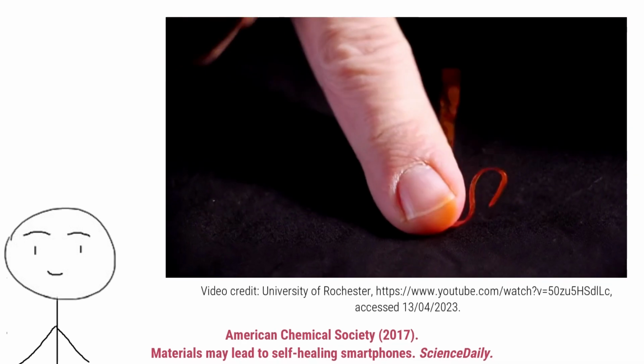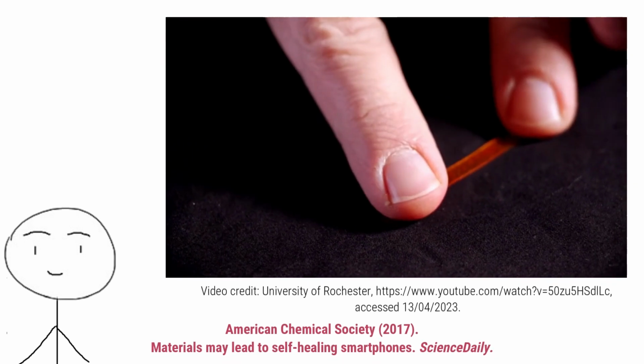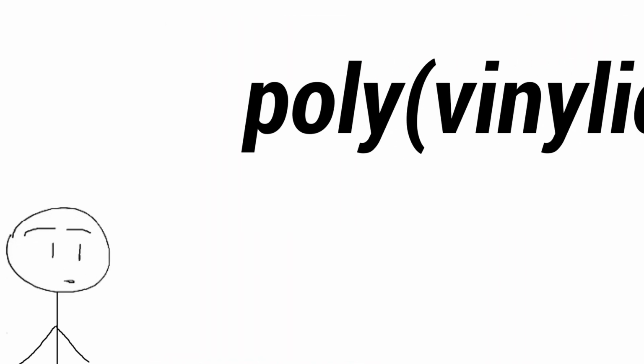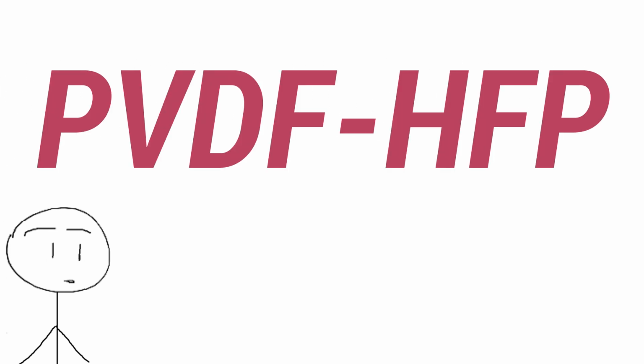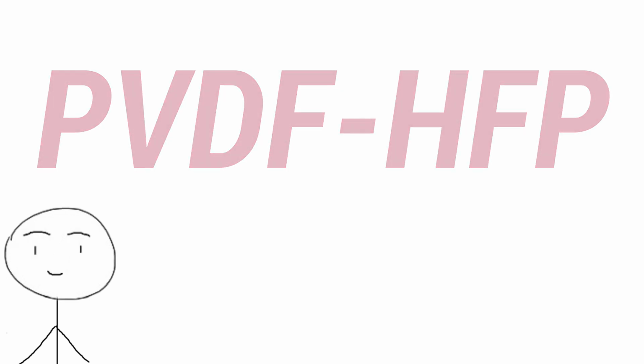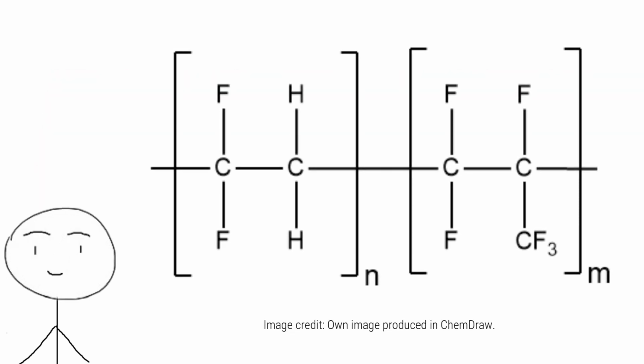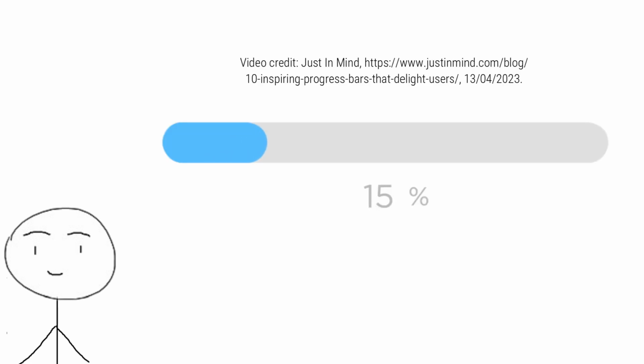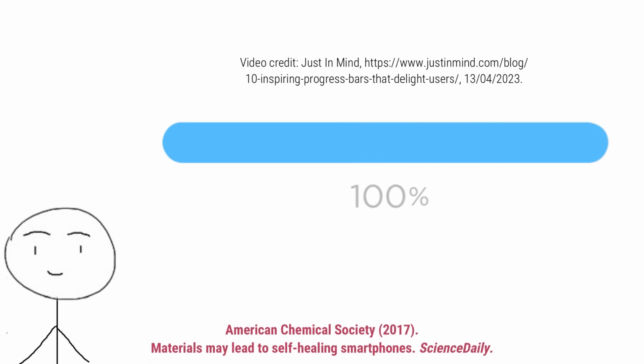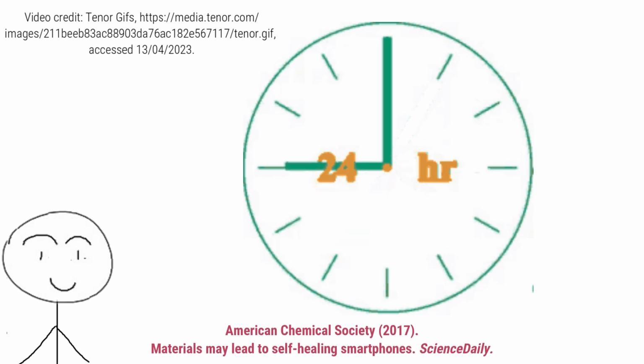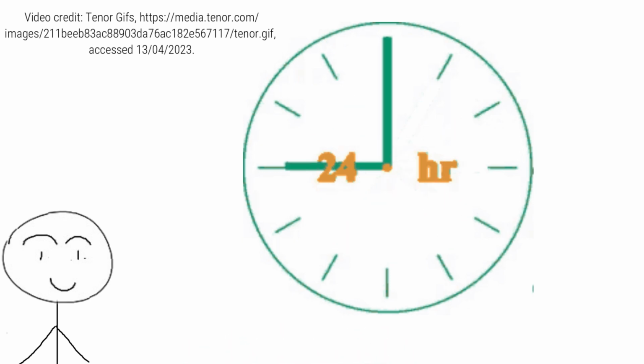Not a problem, bud. In 2017, researchers at the University of Rochester discovered an SMP that uses ion-dipole interactions as reversible net points to heal itself. Introducing polyvinylidene fluoride cohexafluoropropylene, or PVDF-HFP. PVDF-HFP actually exhibits self-repairing properties, and these properties are actually quite impressive. The research team have run tests on PVDF-HFP and found that amazingly it can restore itself to 100% of its original strength. But it will take you a full 24 hours of compressing it to reach that point.